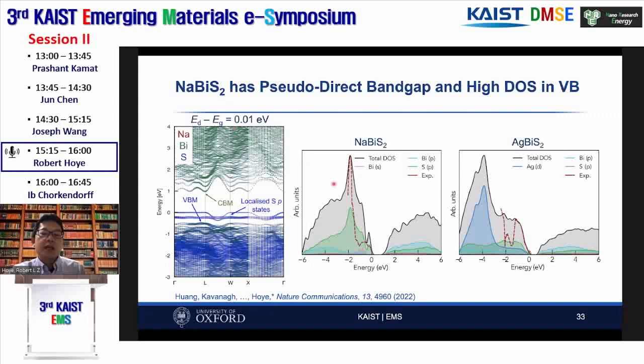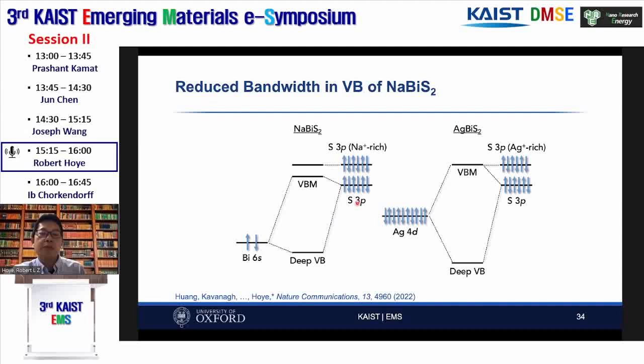Another important thing is that the density of states is concentrated much more closely in the valence band in the sodium-based compound than in the silver-based compound. And this means they have many more states available in the upper valence band to take part in photon absorption processes. And we can rationalize that based on these simple molecular orbital diagrams.